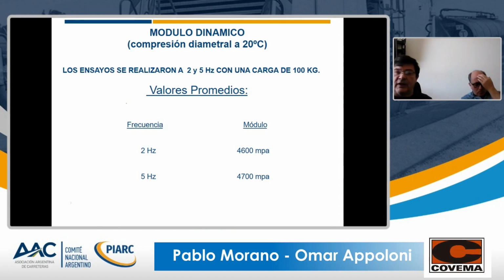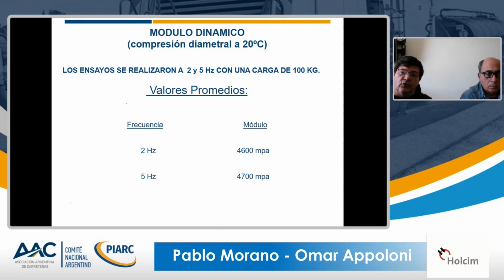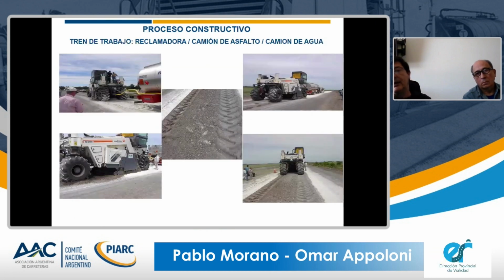to those probes we conducted all of the tests with a dynamic module with 2 different frequencies, 2 and 5 hertz with a load of 100 kilograms, and the modulus we obtained were 4600 and 4700 MPa. That is for the Marshall probes that were taken to the lab.